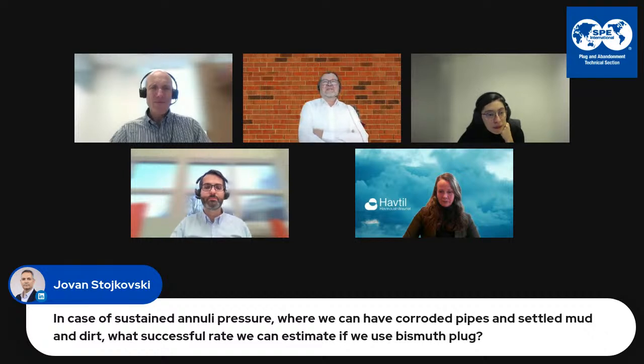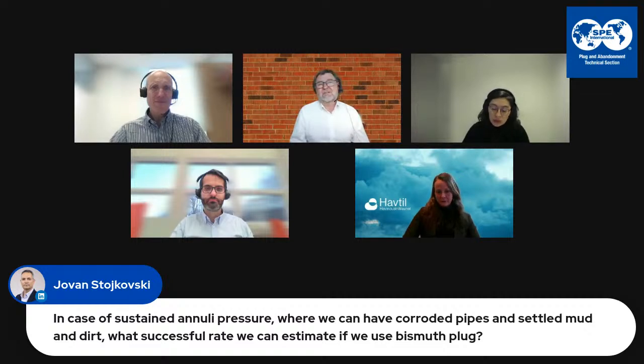This was inside. We placed it inside a conductor, so the conductor was actually in good shape. It was cemented. Some conductors had good cement, some had bad cement, but there was no corrosion that we discovered on the inside because this conductor was 1 inch wall thickness, so it was quite thick, and we didn't notice anything basically there.